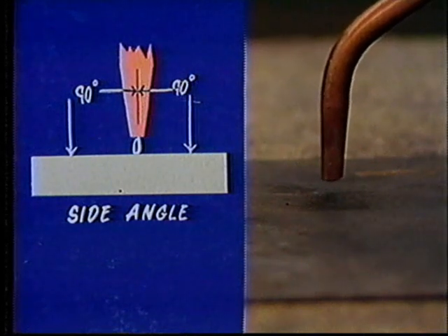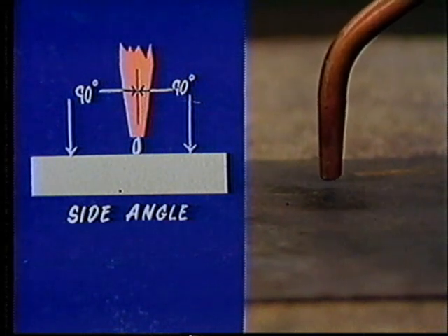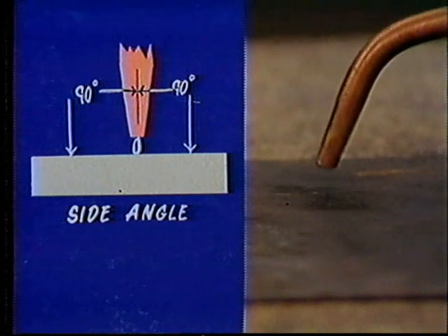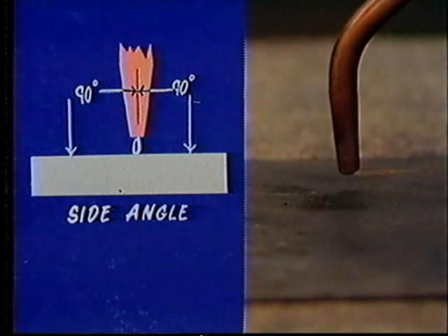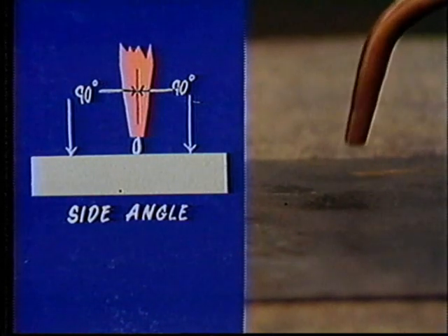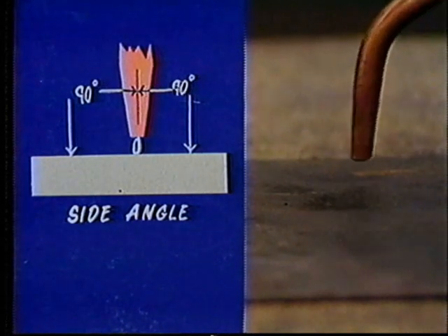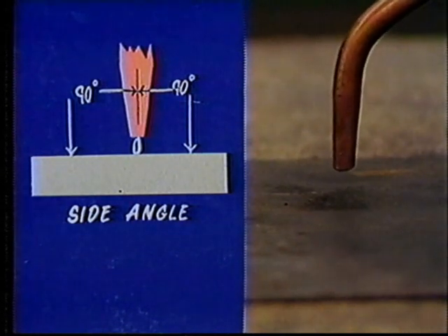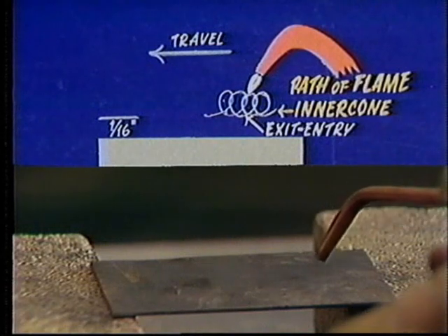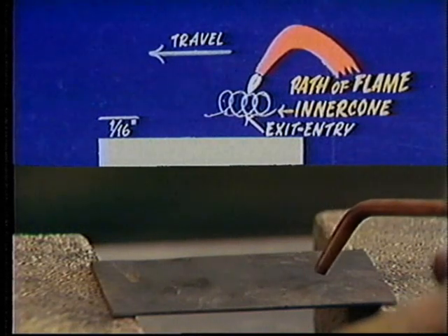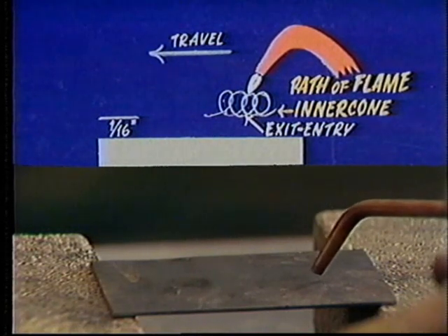Now the side angle here should be 90 degrees. If it's tilted down as it appears there or too far to the other side, it will give you an improper bead shape. And why is an improper bead shape so wrong? Well, it can give you cold lap, and it can produce discontinuities in the welded base metal.